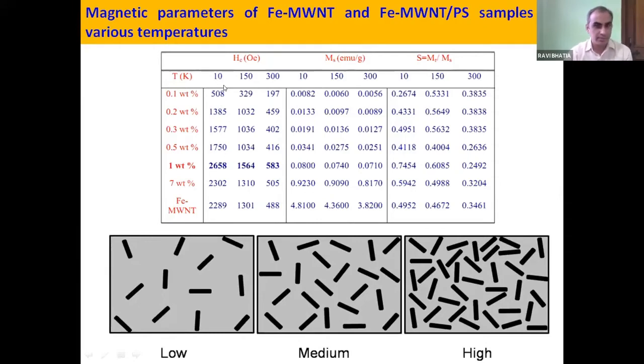What is the reason for this non-monotonic behavior of coercivity with respect to the loading of multi-wall carbon nanotube in the composites? I will again explain what is the important feature here. At all the temperatures, 10, 150, and 300 Kelvin, one can see that the values of coercivity are highest in the case of 1 weight percent sample, and below and above they are decreasing. Here also I must say that there is no theoretical model existing which can explain this particular result.